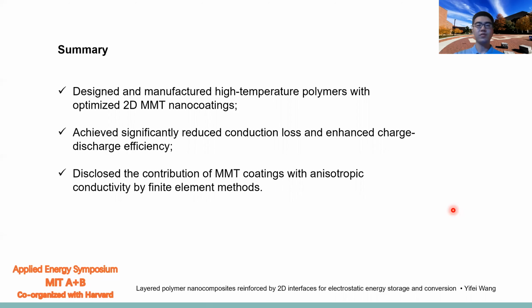So here I will give a brief summary of this work. Firstly, we designed and manufactured high temperature polymers with 2D MMT nanocoatings. We proved that these coated polymers show reduced conduction loss and enhanced charge-discharge efficiency. And from the finite element simulations, we disclosed that these MMT coatings with anisotropic conductivity can have a very significant influence on the current density distribution, electric field distribution, and also the temperature rise.